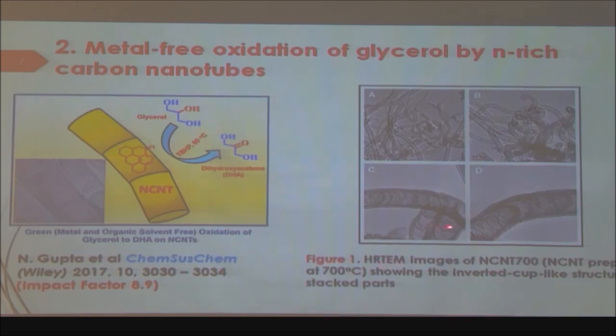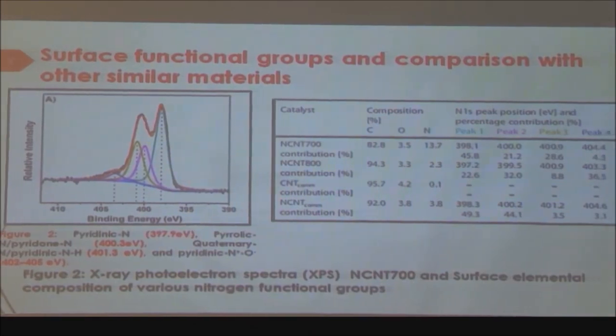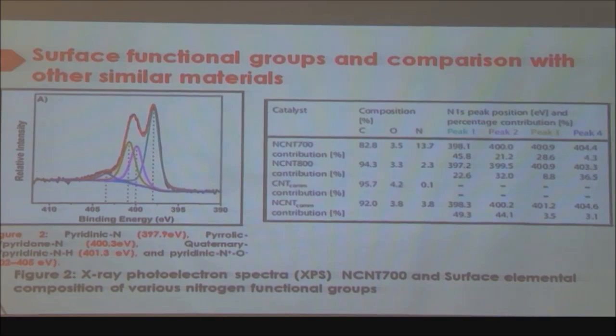And the dimensions are 10 to 50 nanometers. So they are not very big, most of them 10 to 20. So they are carbon nanotubes, not nanofibers or some other material. Once we make them, you can see that these are very beautiful fibrous structures that we get. Once we make them, we try to know whether nitrogen is there on their surface or not. So how do we know it? By the characterization technique of XPS.